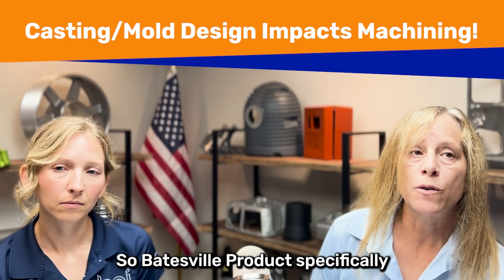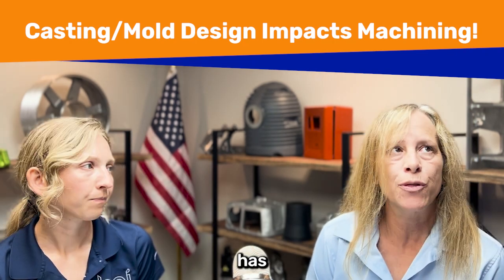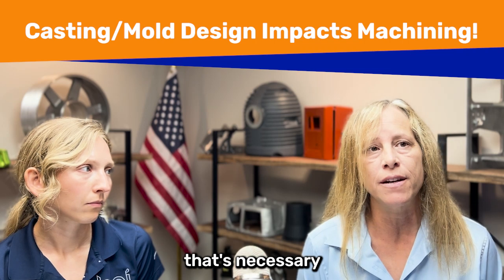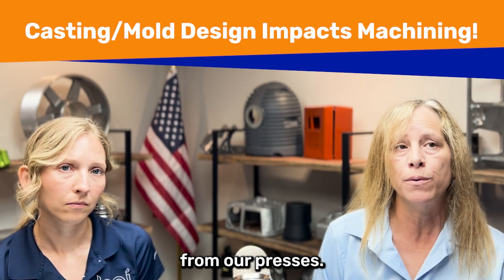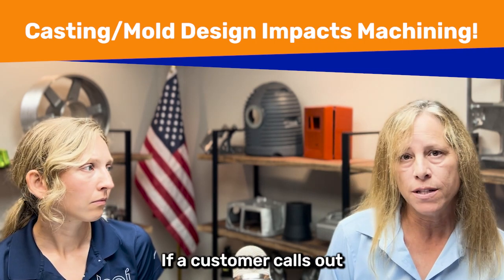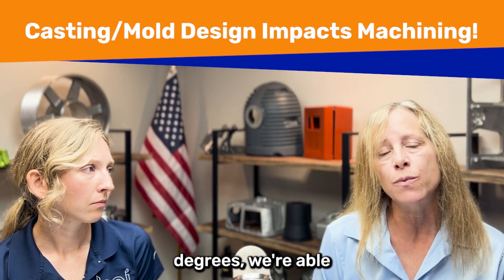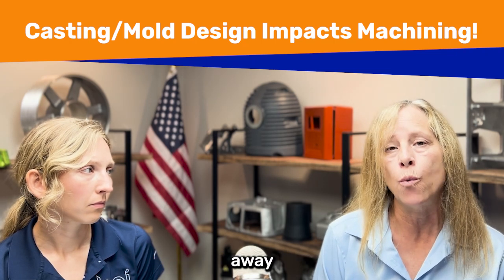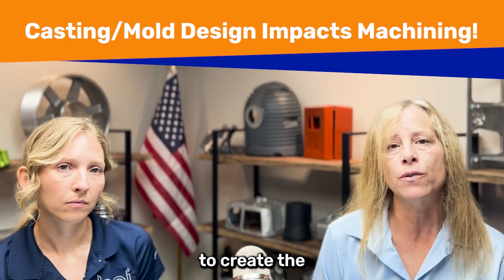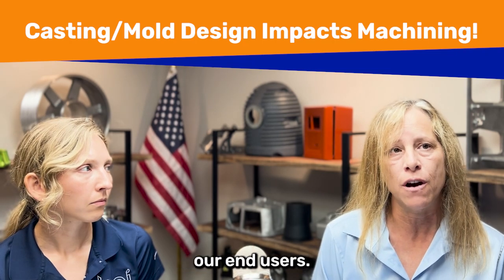Right, so Batesville Products specifically has a 3-degree draft that's necessary for our parts to eject from our presses. If a customer calls out for something that's less than 3 degrees, we're able to machine that material away from the casting to create the tolerance needed for our end users.